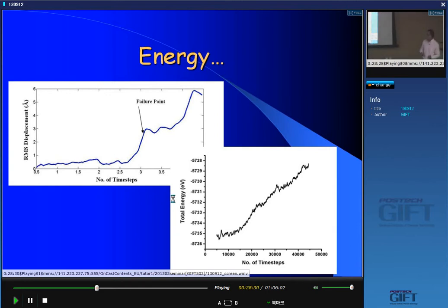Okay? And I'll do this simulation over and over again. Actually, in this case, we have done it for something like 110 times. And each time I'll do it for a different input combination. That means my shear velocity will be different, my grain size thickness will be different, and so forth. So I'm trying to generate information, like this room analogy. I do not need to simulate every chair here, but I'm trying to simulate some of the crucial chairs so that I can put them together later on and construct a total model for the whole system. All right? So that is how it is calculated. At the moment the slope changes here, I find out how much energy has been there. That is the energy that I have done for this system, and so on and so forth.